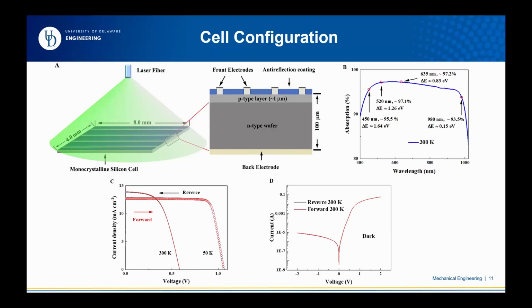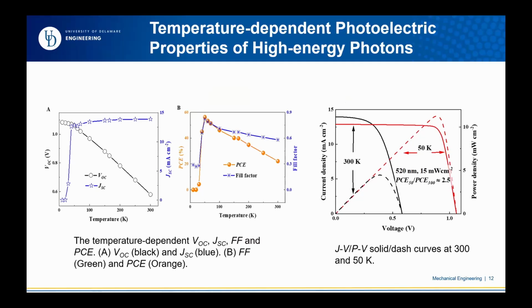And here is the reverse and forward characteristic, showing how these cells work. They work perfectly. We look at both room temperature and 50 Kelvin. You can see at 50 Kelvin the curve looks really nice, right? It's really nice. You can easily see the fill factor is much higher compared to 300 Kelvin. We also did this in a dark room, and the curve is very typical. So we make sure everything is fine, and we test the open circuit voltage, the current density, and the fill factor, and then we calculate the power conversion efficiency, PCE.